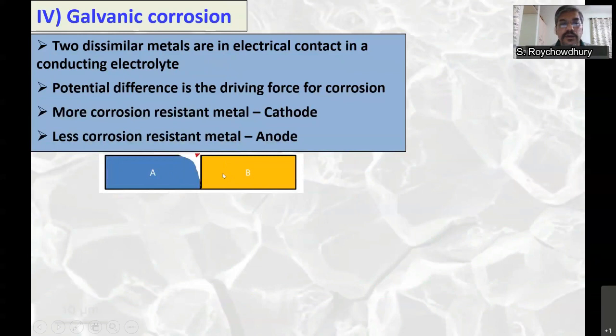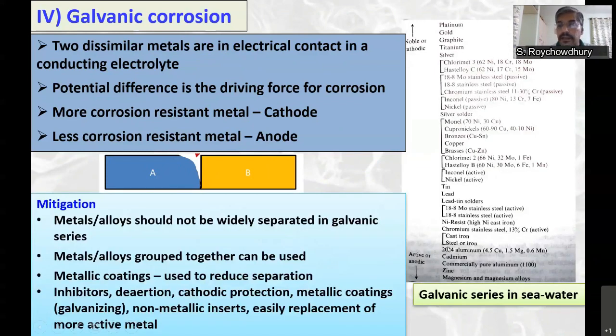If they are in electrical contact, then metal B will preferentially become the cathode. So the more corrosion-resistant metal will become the cathode. So it will now no longer corrode. And the metal which is less resistant to corrosion will now become the anode, and it will corrode at a much higher rate than what it would have corroded when they were not in contact. Such galvanic couples can be seen from the galvanic series.